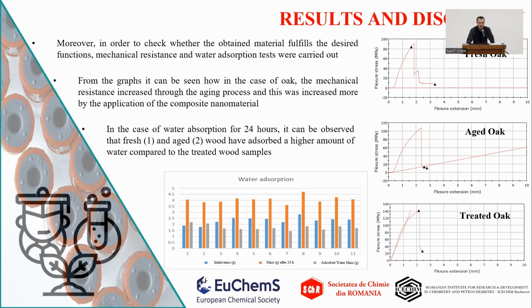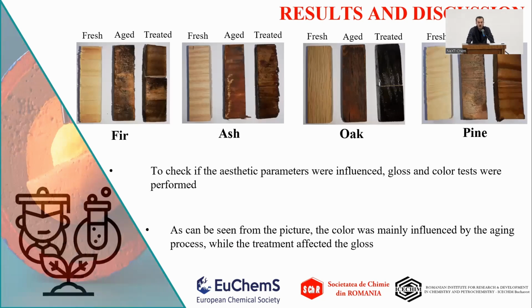And in the case of water absorption for 24 hours, it can be observed from the graphs down below that the fresh wood and the aged wood have absorbed a higher amount of water compared to the treated wood samples. We tried to do some aesthetic tests to check the gloss and color difference. As can be seen from the pictures, the color was mainly influenced by the aging process, while the treatment affects the gloss.